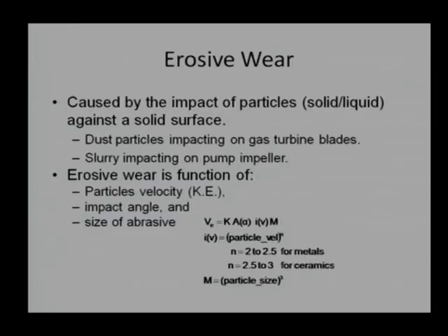This is the equation generally given. So, V is the wear rate. There is some constant, we can say an empirical constant or some probability of how many, after how long, a particle will be detached. Function of alpha, which is a function of impact angle. Function of velocity, and mass, which is a function of particle size.